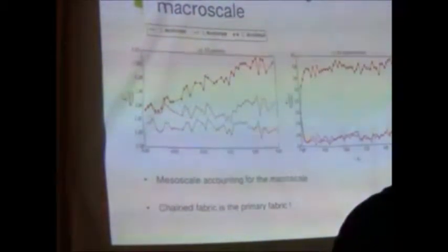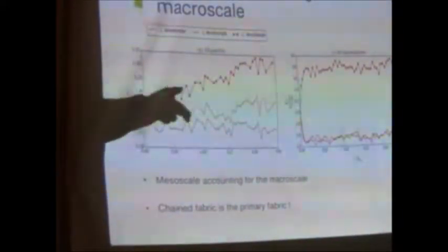And just for the sake of illustration, this is the result you obtain if you compute the autocorrelation function for all particles, without restricting the analysis to the chain particles. You see that even if you have a bigger correlation in the z direction, you don't catch the peak-like curve you obtain for the mechanical response.